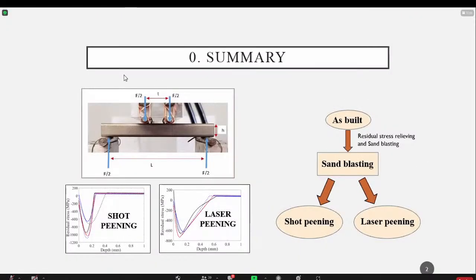So in the present work, we 3D printed a prismatic, rectangular shape titanium alloy specimen, and a group of those specimens were subjected to laser peening, and another group received shot peening. The aim of those technologies is to set a certain compressive residual stress profile that changes the way the cracks behave in our specimen. In most cases, thanks to these superficial compressive residual stresses, we are almost inhibiting the superficial crack initiation. So we are forcing the cracks to initiate from the interior or the internal defects, which is kind of curious because in most works they are trying to inhibit this from happening, and we are trying to force it to study how it behaves.